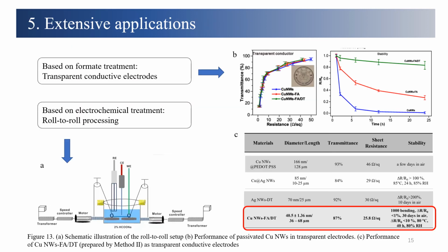These methods have been proved to extend to other applications. Based on the formate treatment, it can be used in transparent conductive electrodes, which show good conductivity and anti-corrosion feature. In addition, because electrochemical treatment can operate at room temperature, this method can extend to roll-to-roll processing. What needs to be pointed out is that in the application of the formate technique, acid condensation with a pH less than 3 must be avoided.